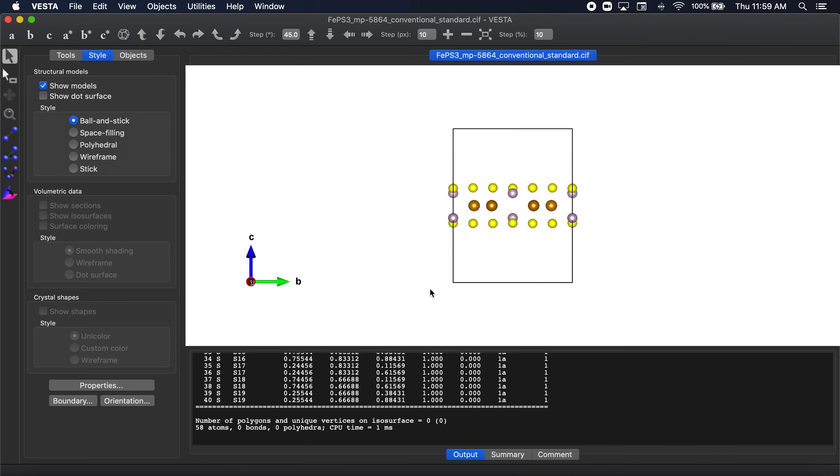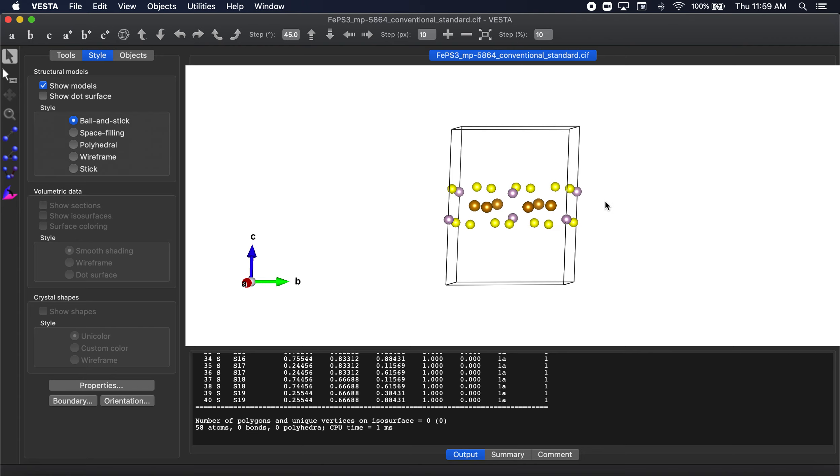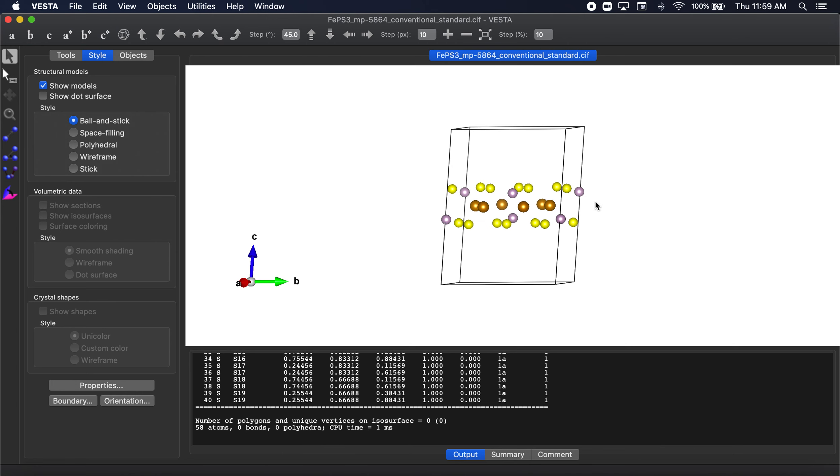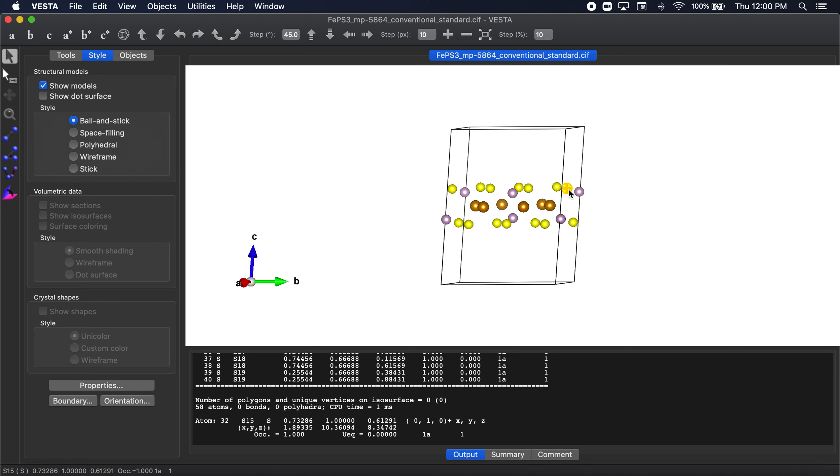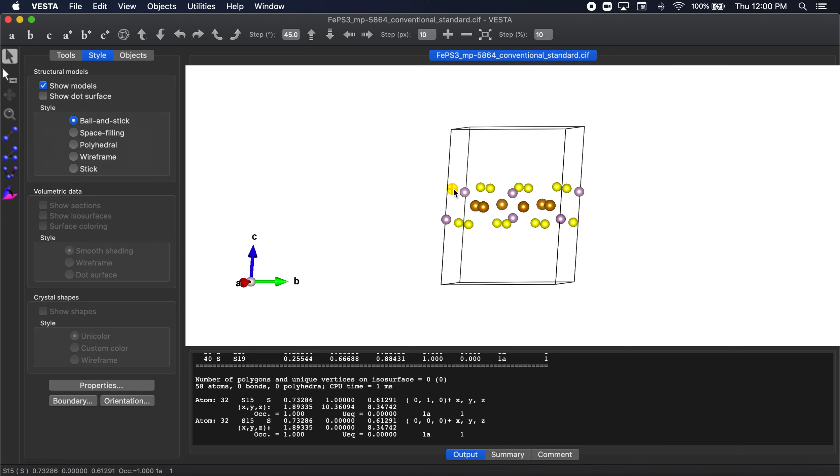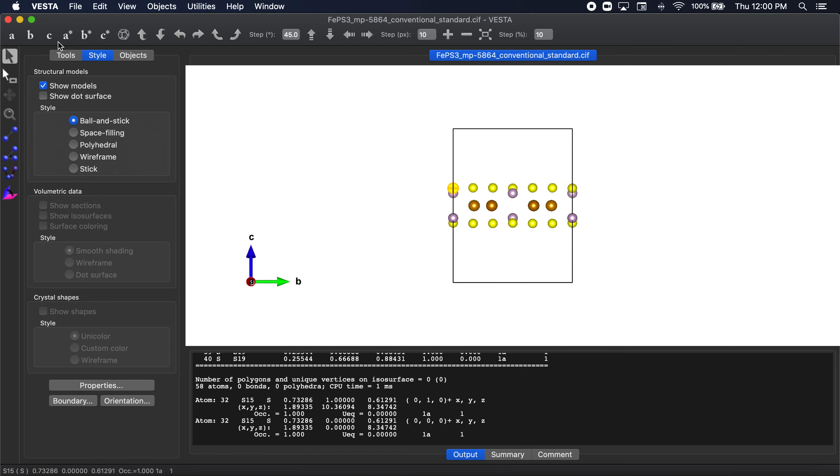And obviously we don't want to save atoms that are periodic replicas of each other. It may not be obvious, but for example, you can see if we save these atoms that are replicas of each other, this doesn't make sense because when we go put this into electronic structure calculations, it'll think we have double counted an atom and they actually will tend to crash. So for example, this sulfur atom is S15, you can see they're both atom number 32. So if we include these both in our file, you'd be double counting atoms and you simply would have an inaccurate structure.